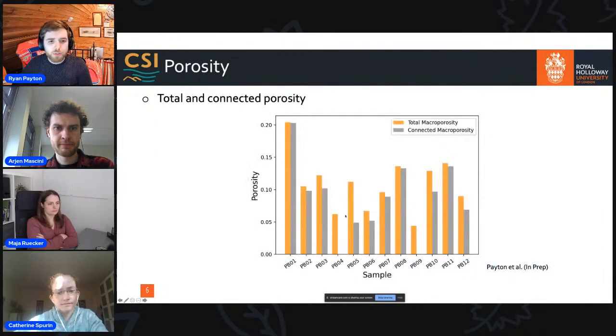These are the porosity results from the Porcupine Basin. There's a bit more variety which we were able to pick up. We can see there's a bit more of a discrepancy between the connected and total porosities as well, which is something which is really interesting. Our results are around the 10% porosity mark, which is a really crucial value, and you'll understand why this is as I get into the next few plots.